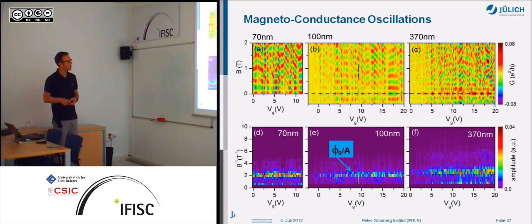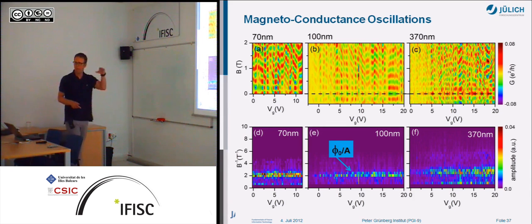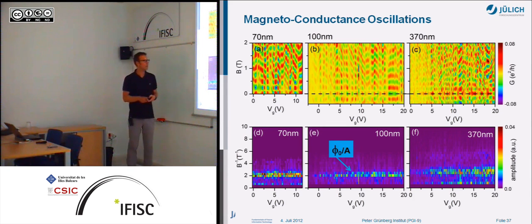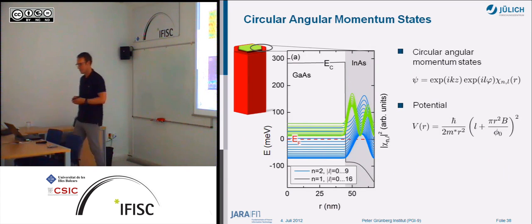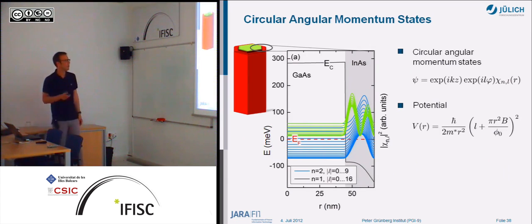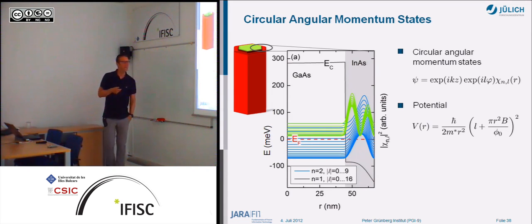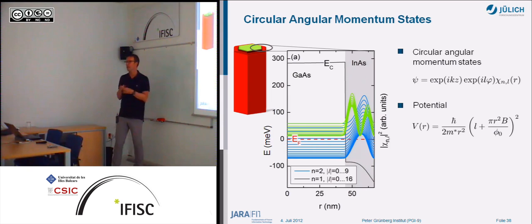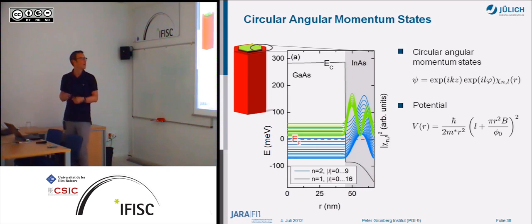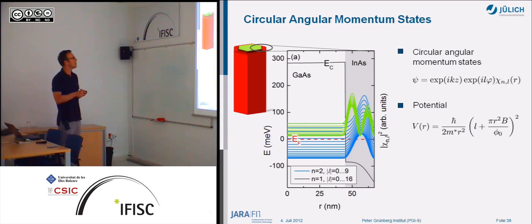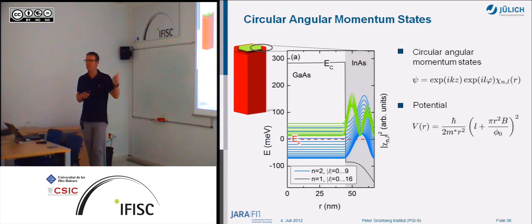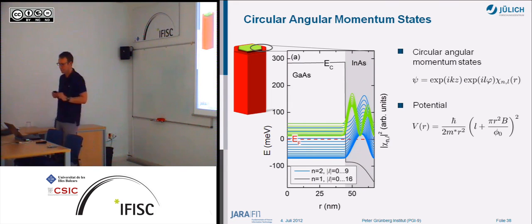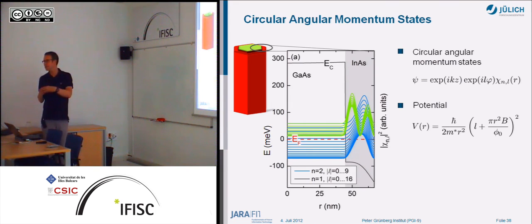And if you do the Fourier transform, you see that for each gate voltage, you basically have the peaks at one fixed position, which is compatible with one flux quantum in the cross-section of the nanowire. So what is the origin of these flux periodic oscillations? You can first think that it's kind of an Aharonov-Bohm effect, where you have trajectories of electrons going around this nanowire. But the nanowire is pretty small. We're talking about 100 nanometers here, with a 20 nanometer thickness of the indium arsenide shell. So it's a pretty small object.